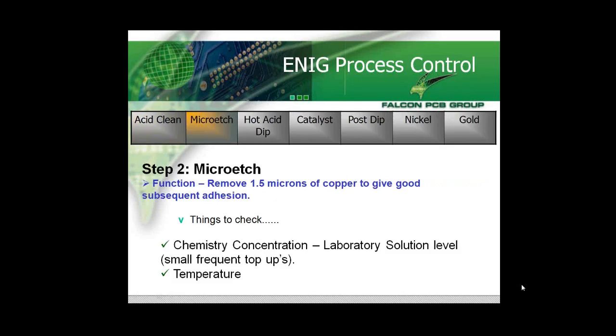Second process, micro-etch. I think Nigel had got 2 microns of copper. We tend to remove 1.5 microns of copper, and we're looking there, of course, to get a good chemically clean copper for the subsequent processes. Again, the checks we perform are laboratory solution levels and also temperature.